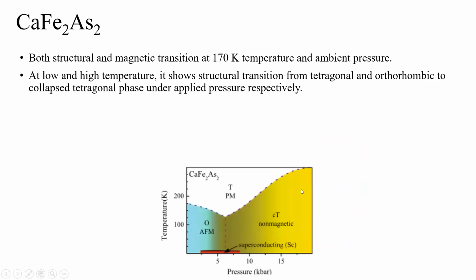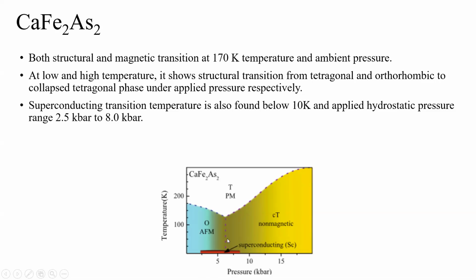As you apply some pressure, these compounds also show a different type of structural transition, from the tetragonal phase to the collapsed tetragonal phase. Interestingly, this collapsed tetragonal phase has no local magnetic moment ordering, whereas iron is expected to have local magnetic ordering. Within this small pressure range, it also shows a superconducting phase below 10 Kelvin. However, people are still trying to understand which particular phase is responsible for the superconductivity: the nematic fluctuation coming from the nematic phase, or the spin fluctuation coming from the orthorhombic antiferromagnetic phase, or the collapsed tetragonal phase.